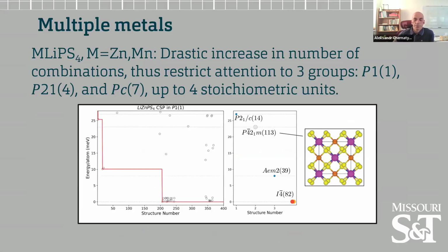Next, we looked at the situation when we don't have a single lithium, but a lithium combined with another metal. This is a standard idea that one can use in order to develop a different chemistry, because if you substitute for the lithium a metal that has a different oxidation state, then one has the potential to generate a number of vacancies in the structure. And these vacancies, of course, would hopefully be beneficial for the ionic conductivity, for example. This is our main driver here.